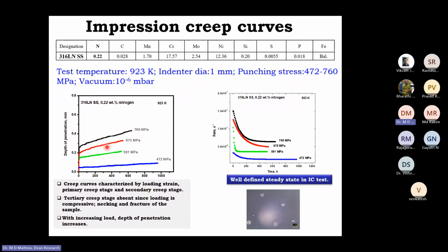From these creep curves, while this is depth of penetration versus time, you can generate the rate of penetration as a function of time graph. And you find that, again, the rate is very high and then it becomes steady. So this is the steady state deformation. You get a very well-defined steady state in the impression creep test. What you see here are the impressions left behind at the end of the impression creep test. One 10 by 10 by 10 sample block was used for carrying out, in this case, 5 impression creep tests.